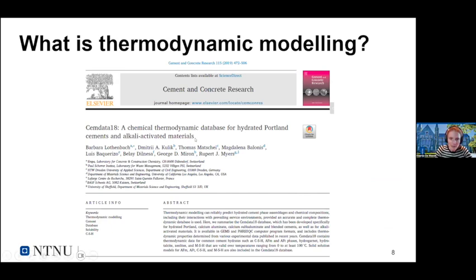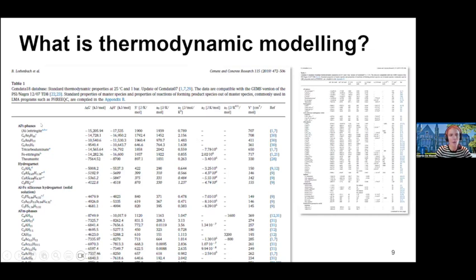And if you look in this publication, you'll find tables with all the typical hydration phases you find in a hydrated cement. For example, here, AFT, hydrogarnet, AFM, and you'll find your Gibbs free energy of formation, enthalpy, entropy, your temperature coefficient, and your molar volume. And not the least, you actually get to know who did the hard work to get you those numbers, so you get the references of the publications. Note that some of these lines are work for an entire PhD. But all that data is available to us, which is just wonderful.